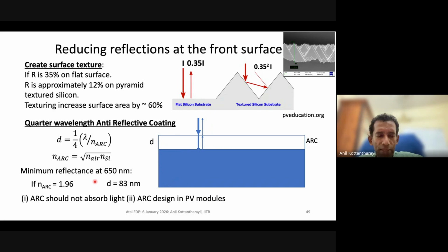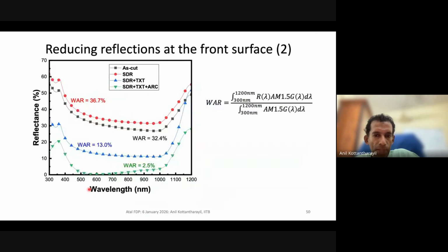in such a design, 650 nanometers, if you want that, then with a refractive index of 1.96, a thickness of the film. So this is usually silicon nitride. Okay, you can use 83 nanometer silicon nitride to basically reduce this. So using these two techniques, the reflections have been brought down to less than 2% in solar cells.